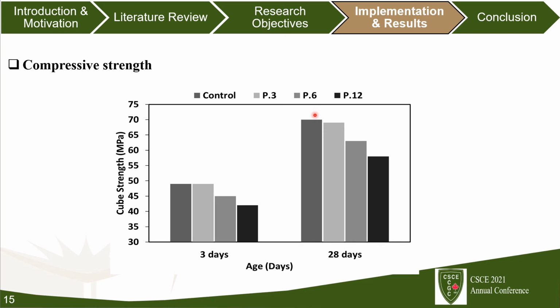control mix. On the other hand, incorporating 6% of microencapsulated phase change material resulted in a reduction in the compressive strength of around 10%, and increasing the percentage of phase change material up to 12% resulted in a reduction of around 15% in the compressive strength.